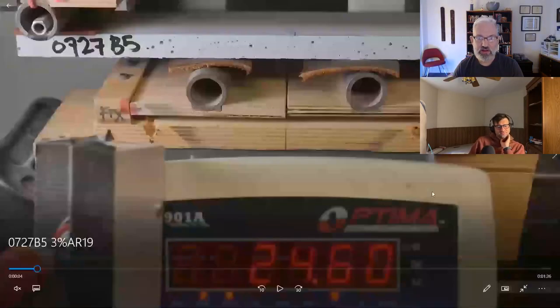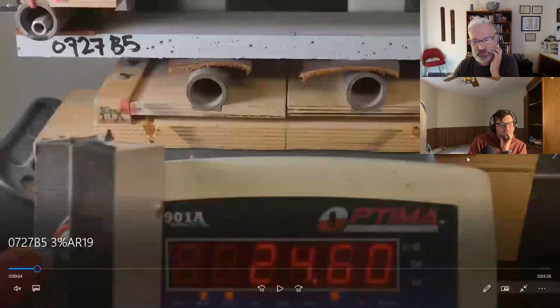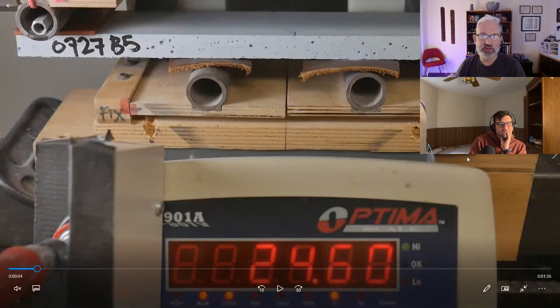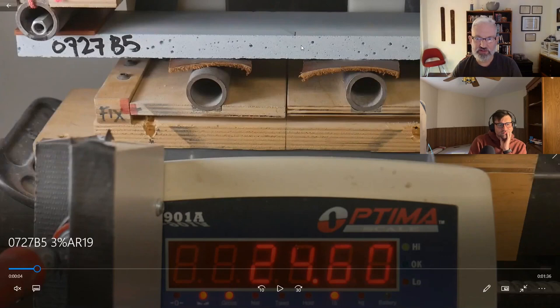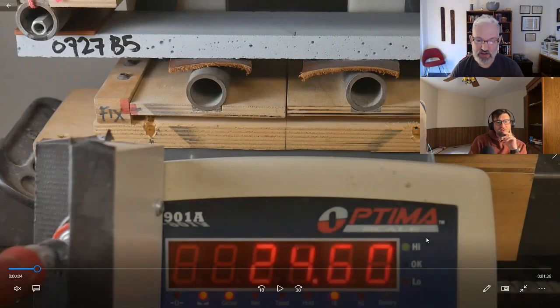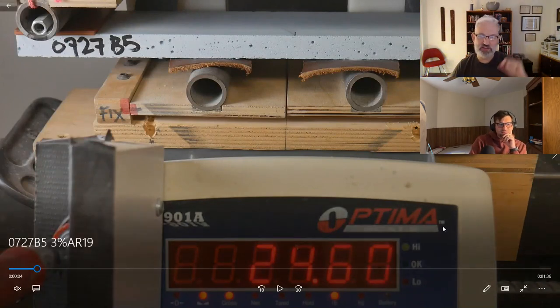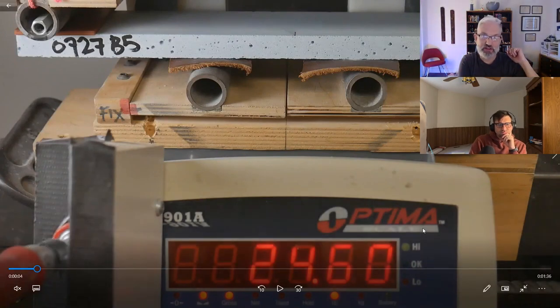This is what's called more ductile, or not brittle. So this is new GFRC. This is a 3% fiber load, a very high fiber load of 19 millimeter glass fibers. The sample thickness is a little different, so you can't correlate the numbers exactly, because even small changes in thickness make a massive difference in the flexural strength of the material.